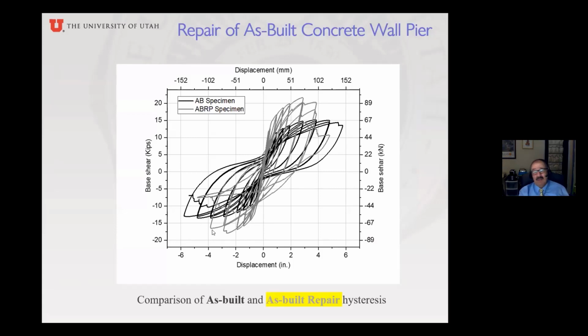And it only went to 4% drift ratio. 4 inches is about 4%. So it didn't go as far as the other one, but it actually maintained pretty well its performance. And then when the bar debonded, it actually pretty much followed the old one. But just remember, this is a repair. This is almost like, you know, rebirth of the wall pier, because this was damaged and now we're actually repairing it.